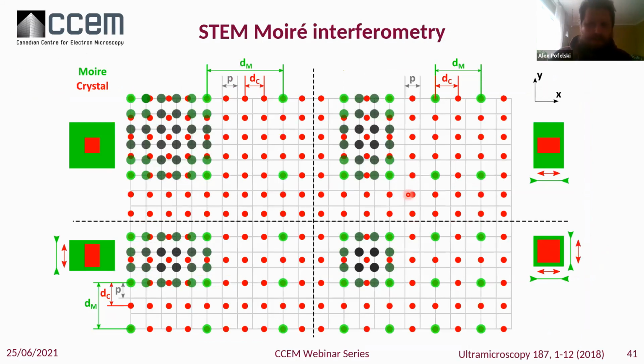So let's try, with an intuitive approach, to see what those Moiré fringes are and how they vary with strain. What you have here on the left is a representation of your scanning grid in gray. In red, you have your atomic columns. And in gray scale, this is the intensity collected in your ADF detector, which is just the geometrical overlap of a certain circular probe with the atomic column. If you're on the atomic column, you have a high intensity, in between, low. You see here that P is relatively close to d_c. We are here in the condition of undersampling. And you can see that the Moiré periodicity seems to be larger, following 5 or 6 atomic spacings in comparison to your crystal lattice here.